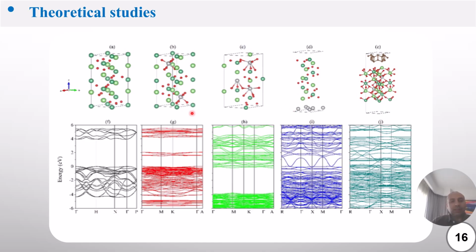We also performed a theoretical study to explain why the band gap narrowed, becoming small or reduced, for different configurations: pristine, Ag at the Nb site, interstitial sites, the heterostructure, and also by adding carbon to the configuration. For example, if we look at the energy density, we can see the band gap between the valence and conduction band is 3.9 eV. This is an indirect band gap. However, when we add the silver, we can create mid-states, and this reduces the band gap.